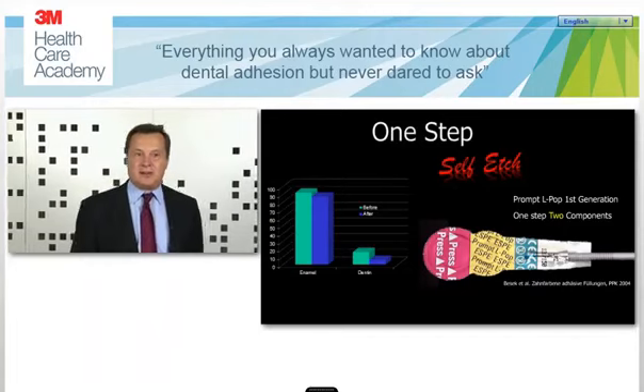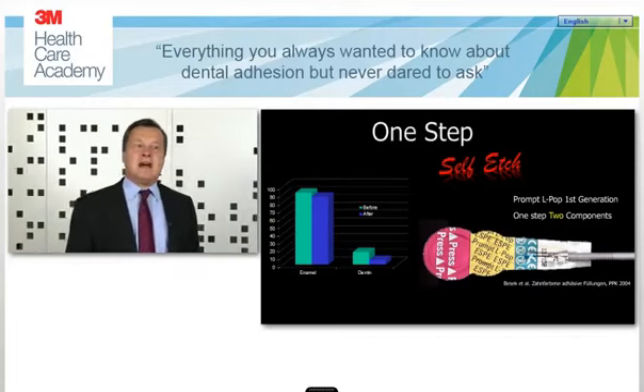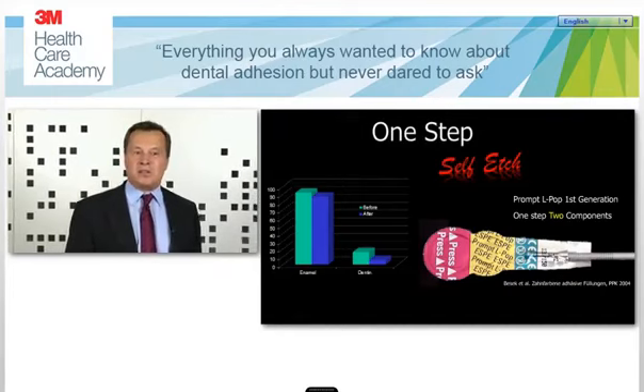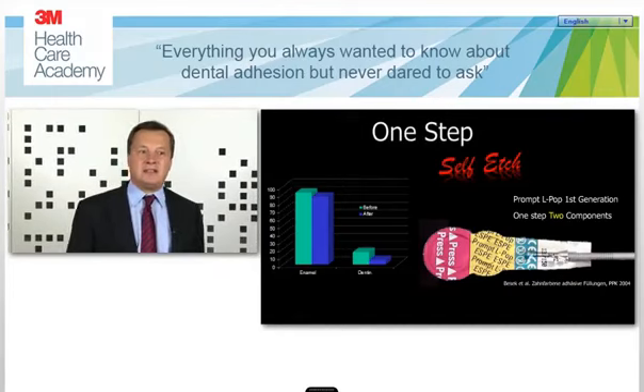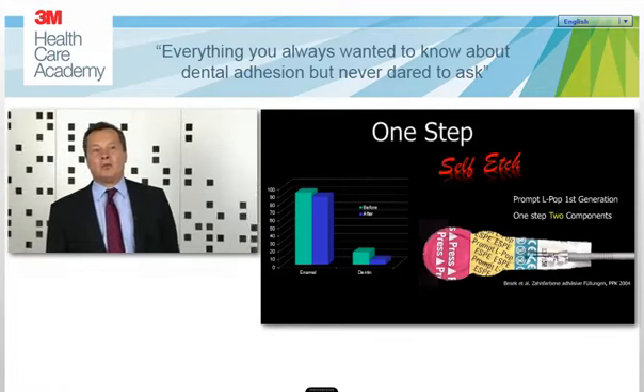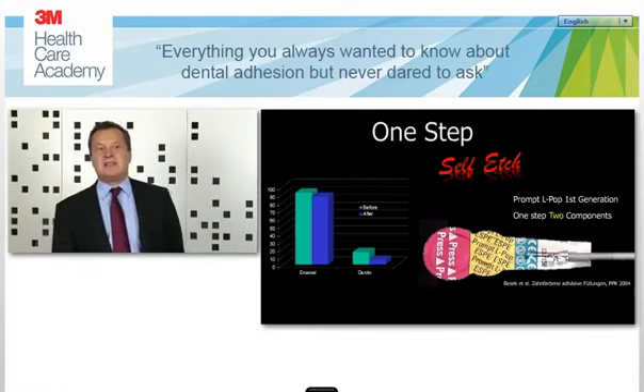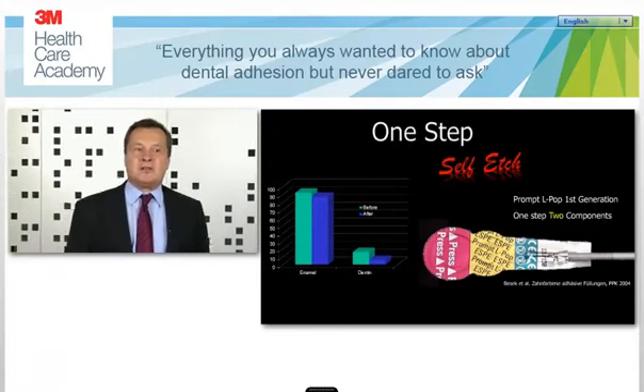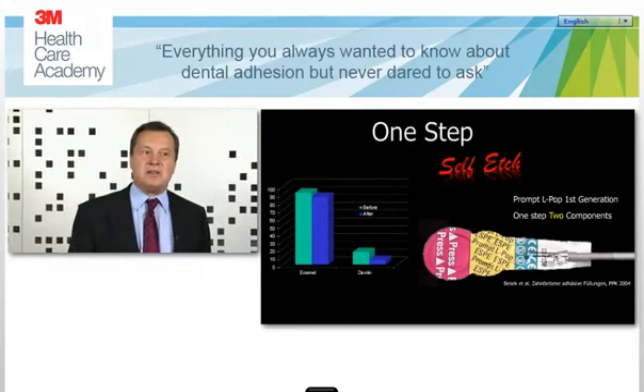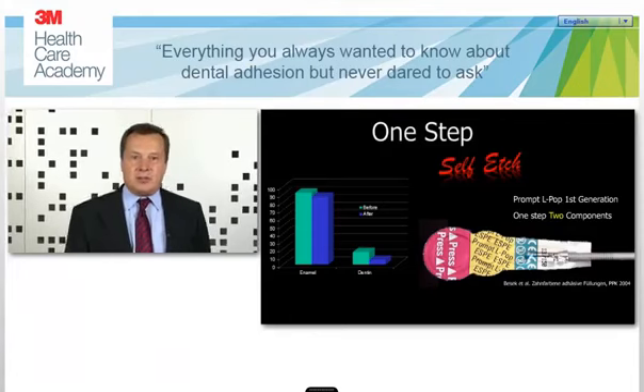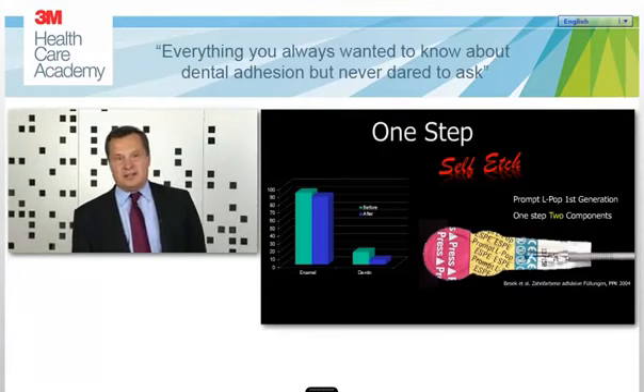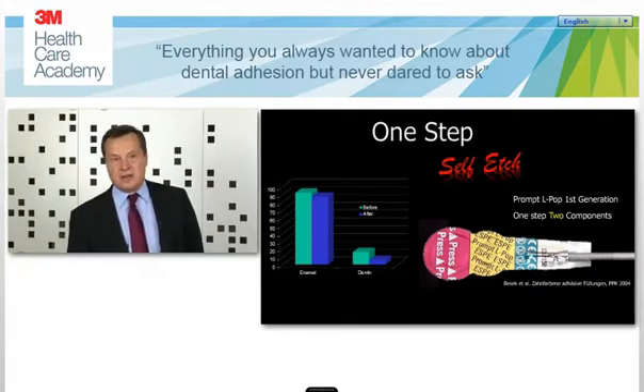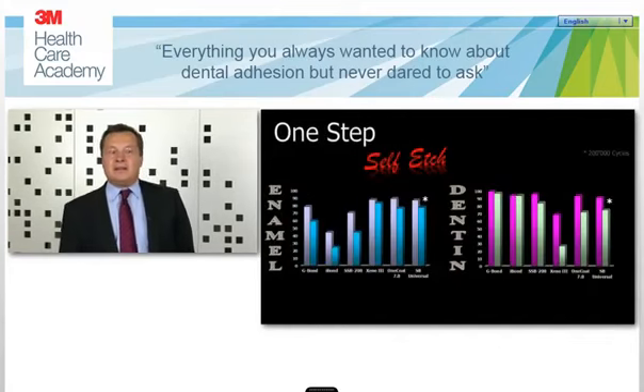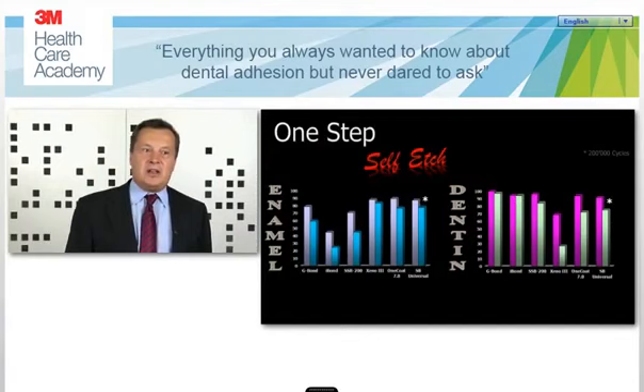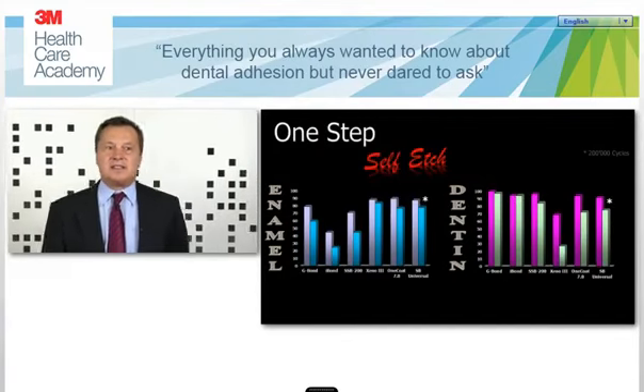And look at the result of such a system. You can see that in our test, the marginal adaptation on enamel was very, very good, as you can see on the left-hand graph. But the marginal adaptation on dentin was quite weak. The reason is most probably that, due to the aggressivity of the acid included in the material, this acid was very efficient on enamel, but it just over-etched dentin. That was most probably the major reason why dentin marginal adaptation was that weak. And this was something which happened maybe 6, 7, 8 years ago.